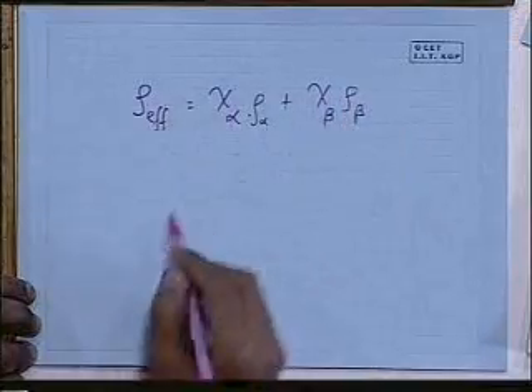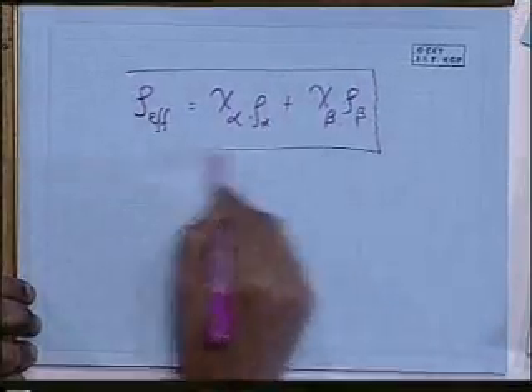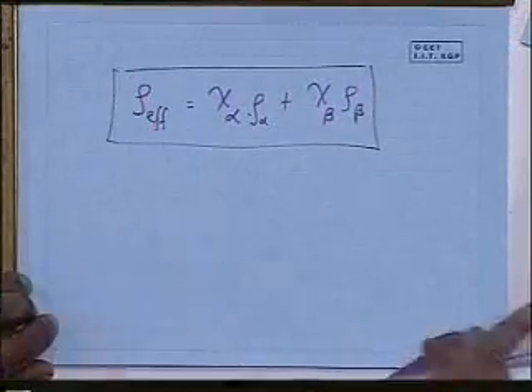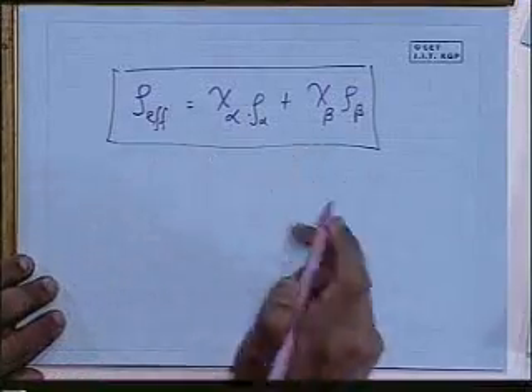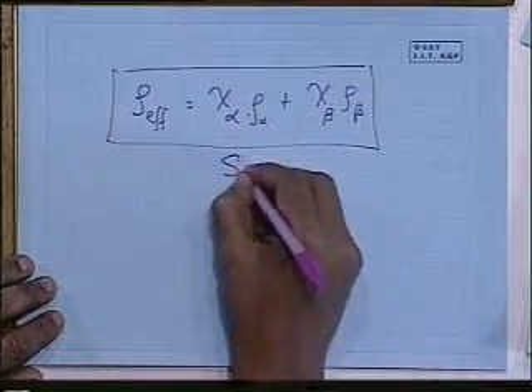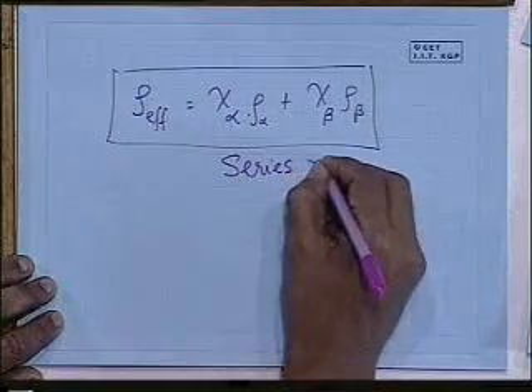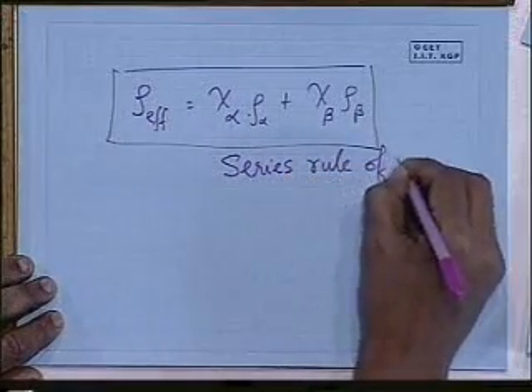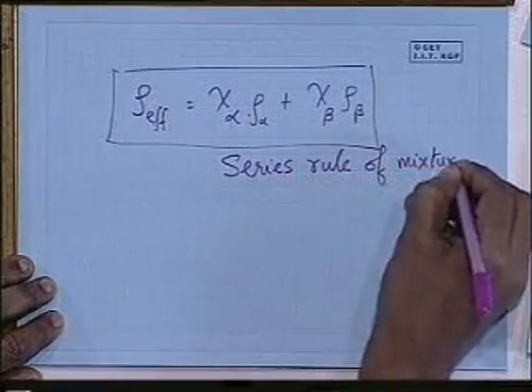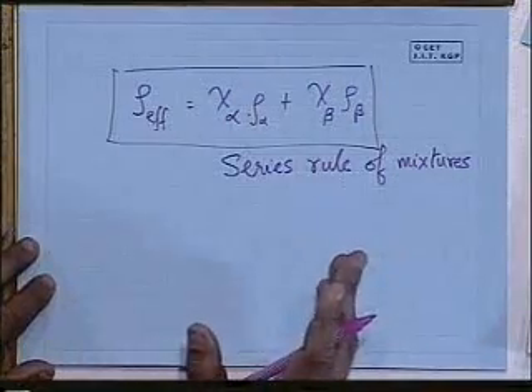So if current flow is perpendicular through these layers, we will express it in these terms. And this is known as the series rule of mixtures. A good approximation when both the phases have similar resistivities. If one is very different from the other, we can't use it. But if they're similar, this is a very good approximation for a random mixture. Even though we've taken an ideal sort of slabs and layers, this is a good approximation for a random mixture.